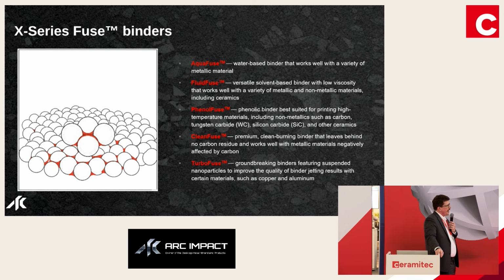Phenol Fuse is a high carbon binder that we typically see with carbide systems where you want a bit of excess carbon or where you want actually a little bit more strength. Phenolic resins tend to be a little bit stronger than these others. They're thermosetting, so once it's cured, it's good to go.